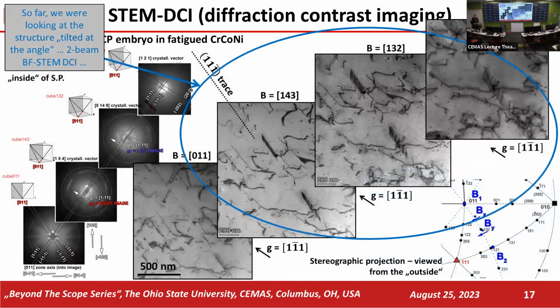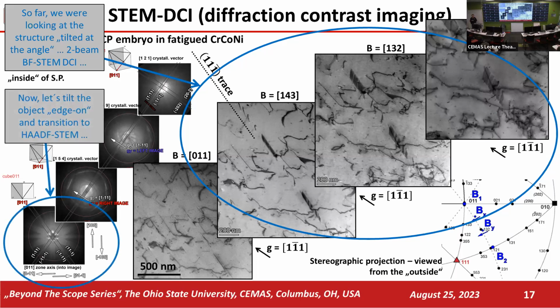So now we were talking about the structure being tilted at an angle. We are using a larger field of view, similarly to CTEM, bright field STEM diffraction contrast imaging. But as I said, our starting point was edge-on zone axis. So let's go back to zone axis. Let's tilt that object back to zone axis, and let's see what other opportunities we have when we are using probe-corrected STEM for such investigation.